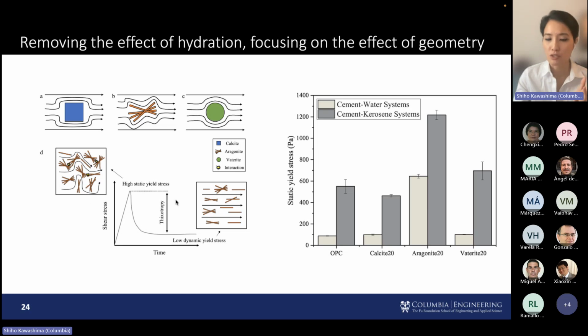But then we also measured that the thixotropy index is very high, right? So relative to static yield stress, the dynamic yield stress is pretty low. And that is because, and this is found in all sorts of suspensions with needle-like materials, under flow, these fiber-like or needle-like materials can align in the direction of flow. And we suspect that the same thing is happening with the aragonite. With increasing shear duration, more and more of it can break down and align in the direction of flow, which is why we can achieve relatively low viscosity and dynamic yield stress while balancing high static yield stress.